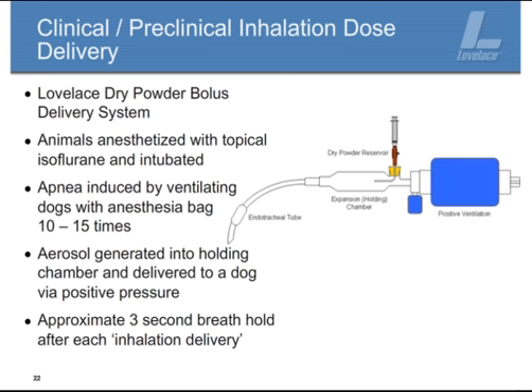And the forced maneuver that we perform is actually performed with a positive ventilation bag, an ambu bag, just like you would see in a clinical setting. In this model for the animals, we anesthetize them with topical isoflurane. After they're anesthetized, we intubate them with an endotracheal tube. Following that, we induce apnea by overventilating the dogs between 10 and 15 times. And for those of you that aren't toxicologists in background, what this does is over-oxygenate the animals. So the animals' internal regulation system that determines how often they need to breathe stops. So the animals are no longer breathing. This allows the teams here at Lovelace to breathe for the animals.